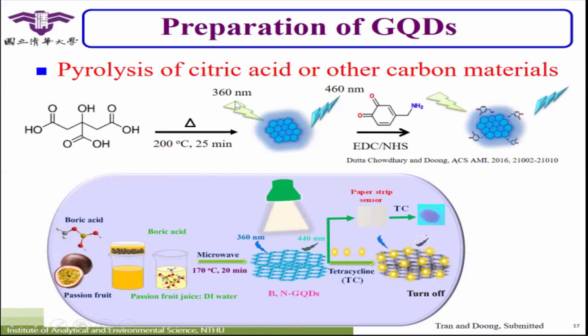Here you can see that when you irradiate the UV light at 360, they can emit at a wavelength of around 460. So their fluorescence property will be good. And we can do surface modification so that they have a lot of optical and electrochemical properties. If you do not have citric acid or other carbon materials on hand, that is also quite easy. We can buy some carbon-based raw materials from the market.